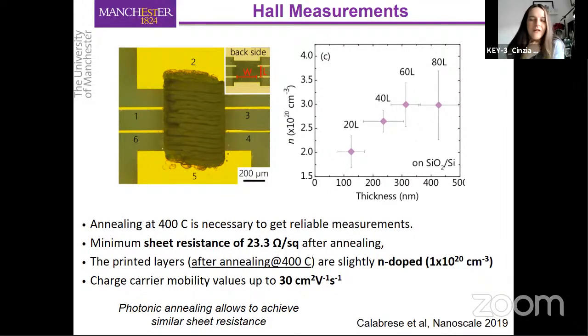400 degrees C. However, Mark has introduced photonic annealing yesterday, and I want to mention here that we have indeed preliminary results where post-processing was done on our films with photonic annealing, and also in our case we observed that it's possible to decrease the sheet resistance by using photonic annealing down to 20-40 ohm per square without damaging the paper. So this is a great technology to perform post-processing on temperature-sensitive substrates such as paper and plastic.